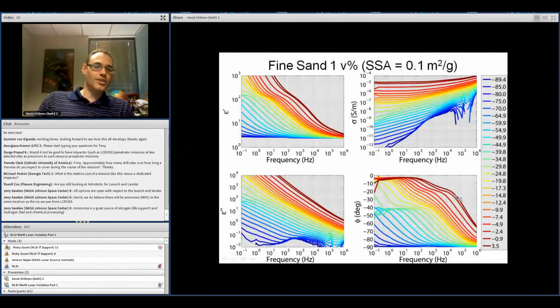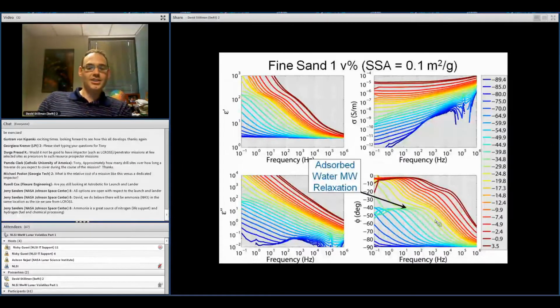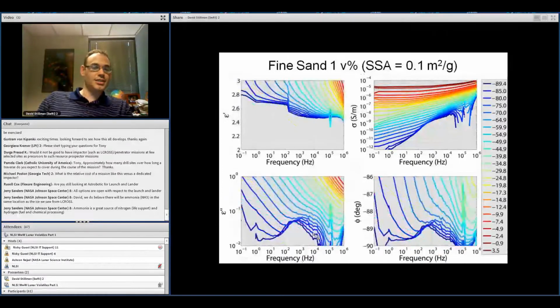So in the LFD, with just one monolayer, all the charges are moving parallel to the surface. Once you add more than one monolayer, the charges can actually move perpendicular to the surface, up and down, and that gives you another relaxation phenomenon. So that's what's going on here, and it drops down and moves out here, labeled with the adsorbed water. And the ice, you can see over here in this plot, and I'll zoom in to show you here. This is a very similar relaxation mechanism to what we saw earlier with the Lake Vostok accretion ice, except it's very small in magnitude because we only have one volume percent of ice in there. And so this shows us that we can actually detect ice in a sample.